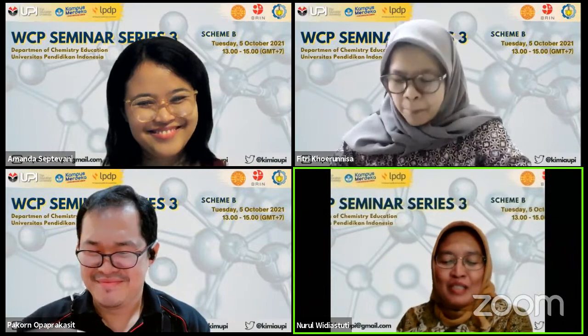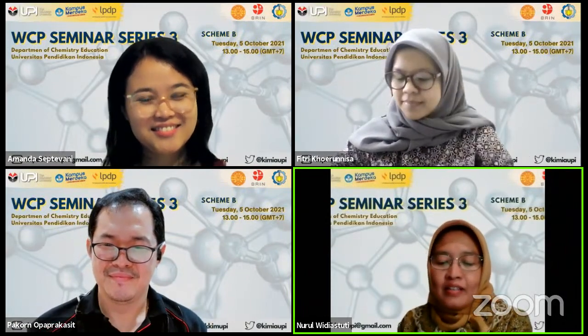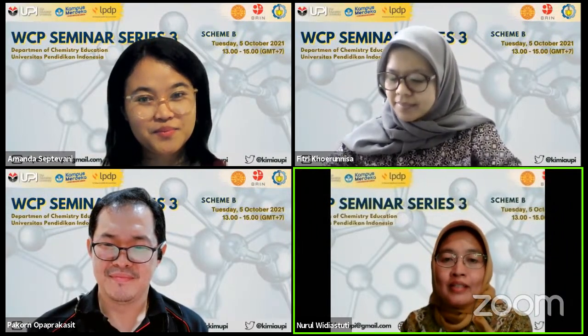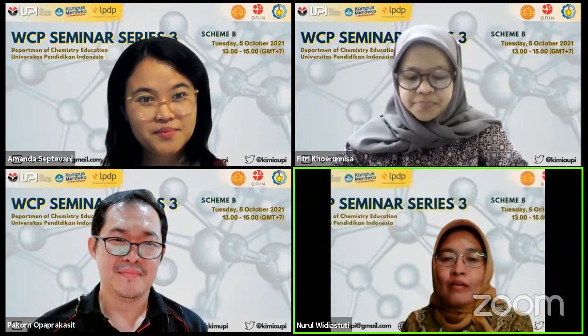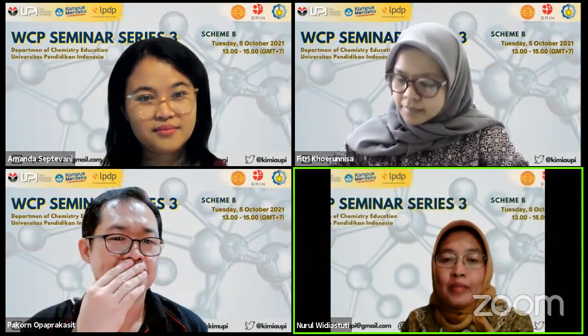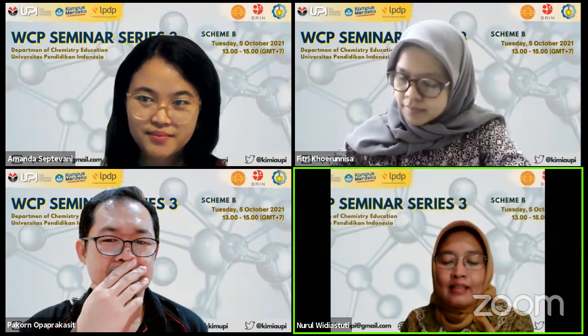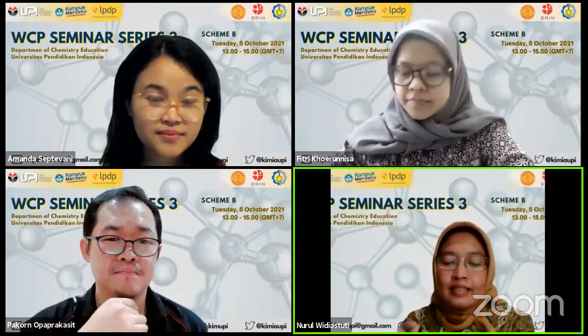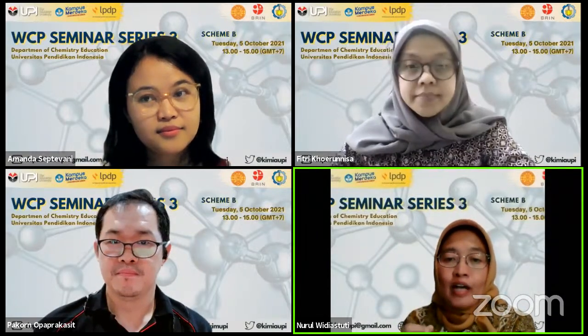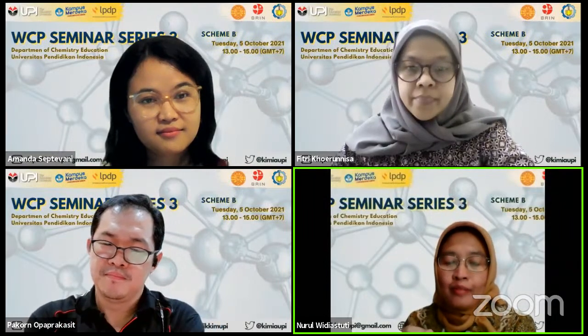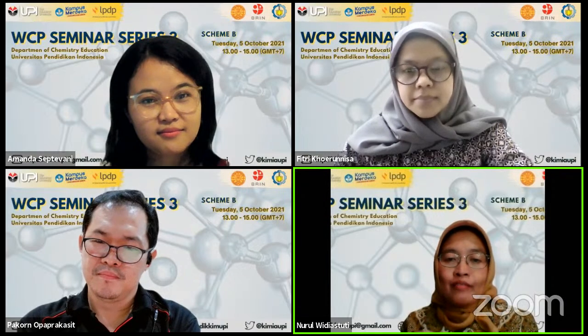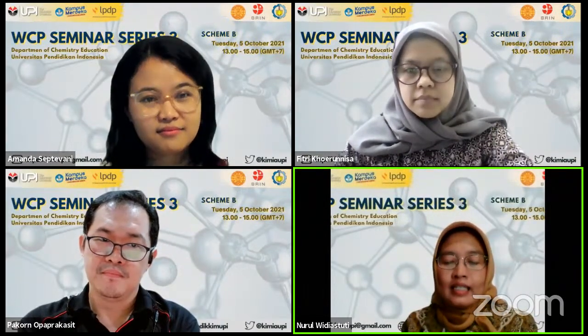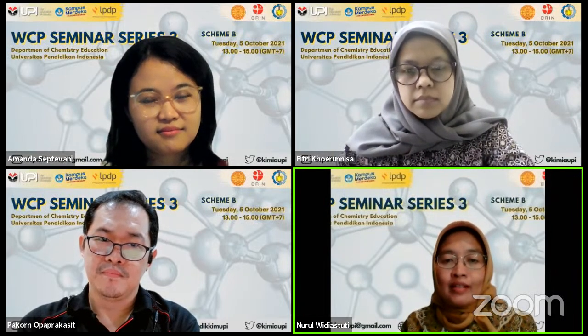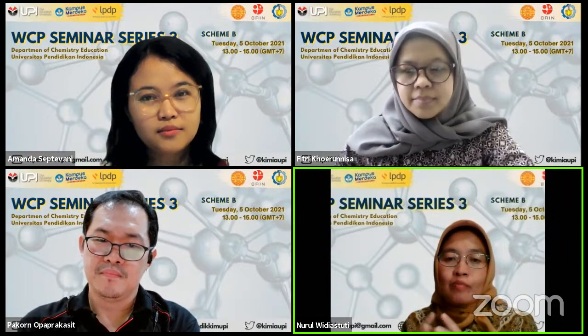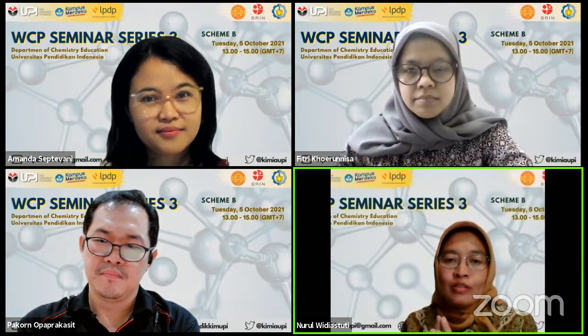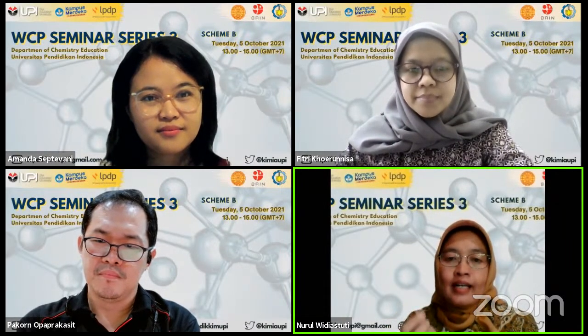Thank you very much for the great question. In our membranes, where we use zeolite templated carbon as a filler in a mixed matrix membrane based on polysulfone, the function of zeolite templated carbon is as a selected material that can design the pore size of the carbon, which has a significant impact on selectivity when we use it for gas separation. Compared to activated carbon, the zeolite templated carbon structure is more homogeneous, the pores are more homogeneous, and they replicate the negative structure of the zeolite.